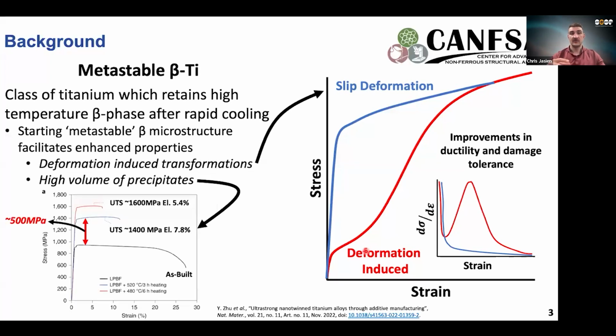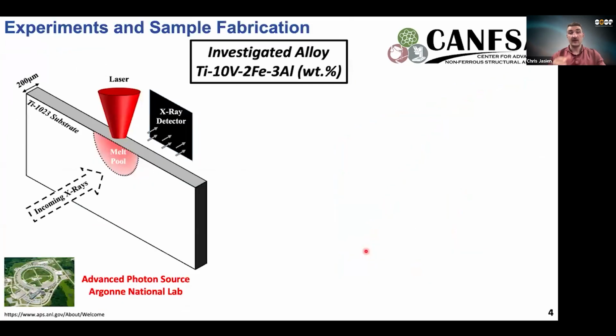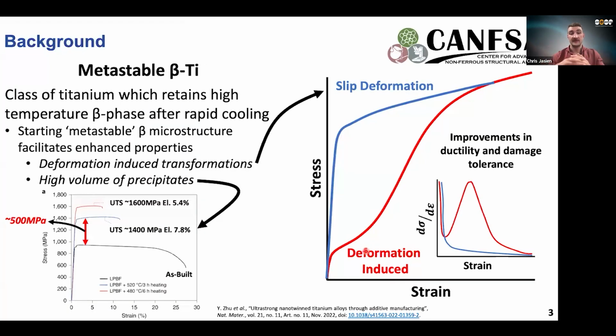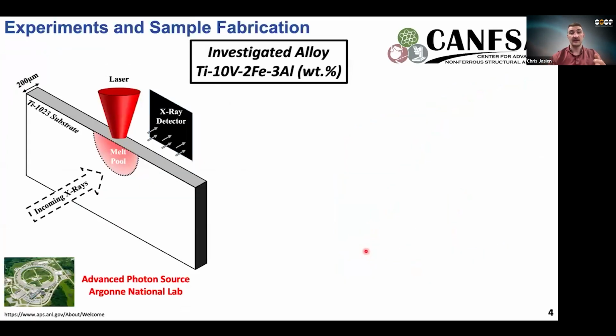Additionally, with the metastable structure, you can get significant amounts of secondary phases that can pop up when you process the material. For instance, some researchers have found that by simply heating and holding the material at a certain temperature, they were able to see upwards of a 500 megapascal increase in strength over a material that was just printed and just tested. So there's a good desire to see where this material class can go. That's where this research kicked off.